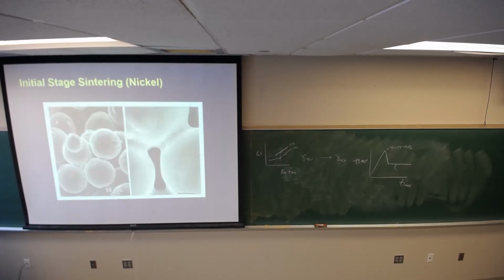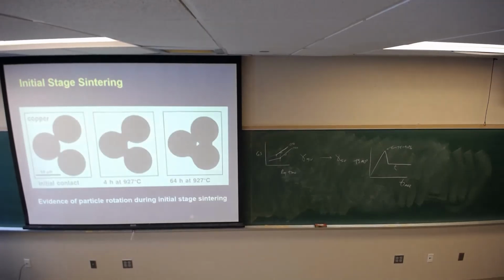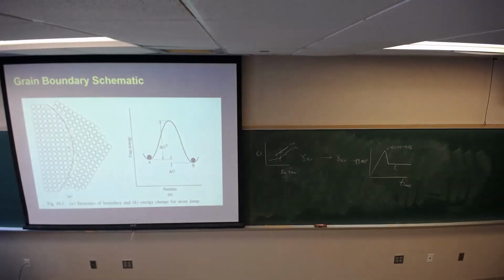Some great pictures taken. These were nickel spheres, and you can see the necks formed. These are pretty high magnification. And then this is really early on. These are for copper, I believe. And they show that the particles are moving. These are 50 micron spheres. These are actually optical microscope images that may have even been drawn. Okay. So we're going to ignore the rest of that.